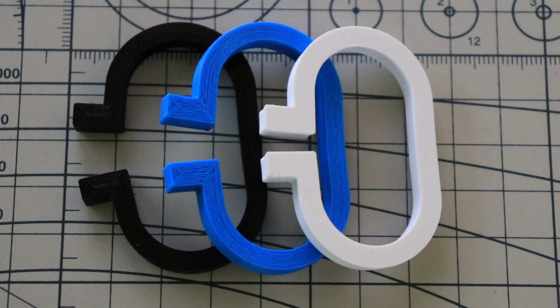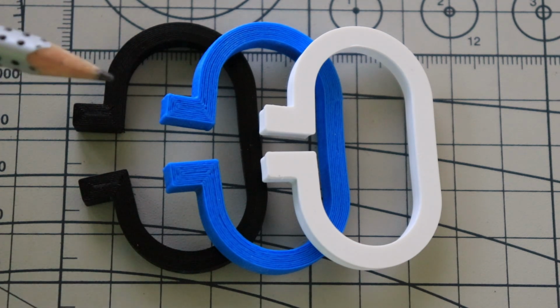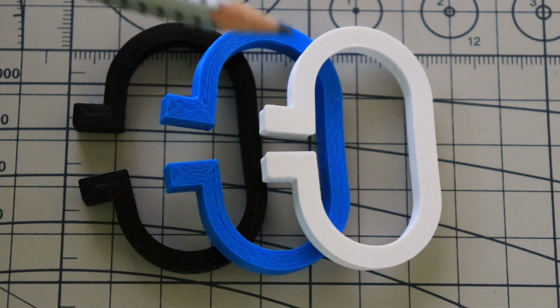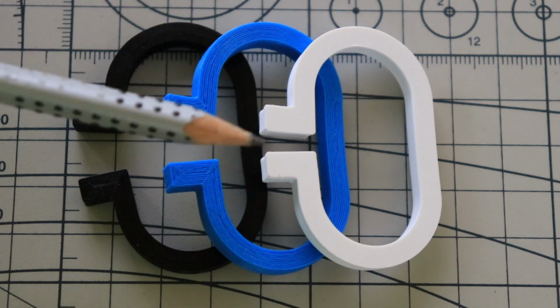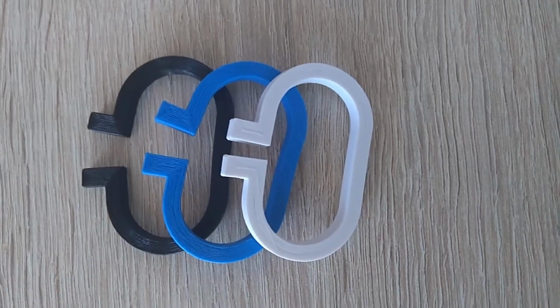And maybe this is interesting information too, after approximately 15 minutes, and this is how they look. So I can see that both PLA have some permanent deformation until the ABS almost got back its original shape. And after 1 day.